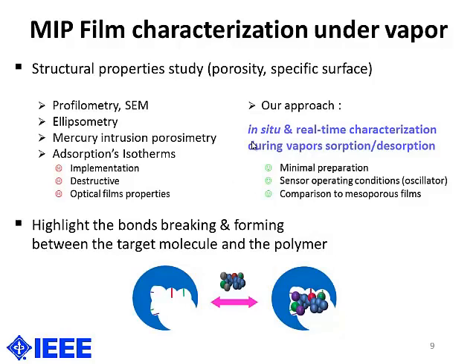Now, our goal in this talk is to show that we can characterize the MIP film in situ with the absorption of vapors inside the MIP film. To study the structural properties in terms of specific surface and porosity, classical ways involve some destructive methods or some optical measurements, which are not always adapted to thin films or to transparent films. Our approach is to use the acoustic platform to characterize the MIP film in situ and in real time, with the monitoring of the resonance frequency during vapor absorption. This will also be a good way to highlight the breaking and forming of the chemical bonds between the target molecule and the polymer.